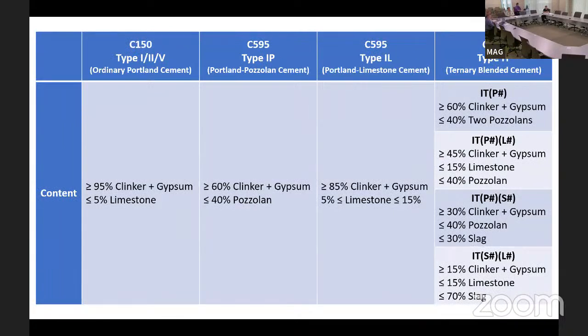Here's a better visual. You have 4 tables here going through. It's all about the clinker factor. You see C150 has the highest percent clinker. And these limestone, pozzolan, and slag, they're considered what they call SCM, supplementary cementitious materials. They have lower CO2 content and GWP weight than clinker. So whenever you're reducing your clinker, you're getting a cleaner cement, a lower CO2 carbon footprint. If you do a full 40% on the IP, you can get down to 60% clinker. The IL, 80 to 85, depending on how high you take your limestone. But the real thing is the IT, if you want to start putting 70% slag and limestone, you can get your clinker factor down to 15%.